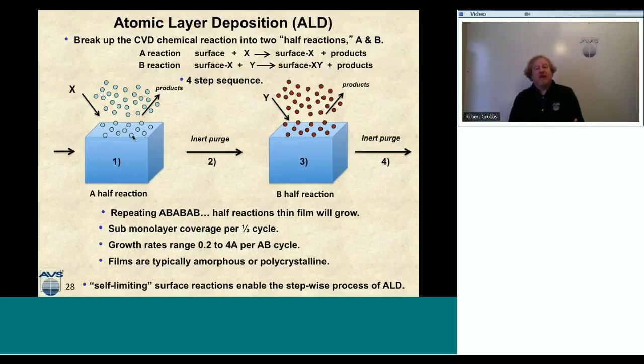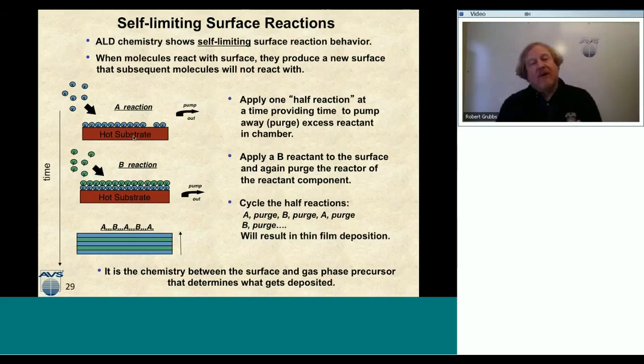So self-limiting surface reactions. This is the word that you need to know for ALD chemistry. ALD chemistry shows the self-limiting surface reaction behavior. So what does that mean? When molecules come down and react on a surface, they're going to produce a new surface. But that new surface will not react with any of those incident molecules coming down onto the surface. And this is considered a self-limiting surface reaction. And this is vital. This is critical to the process of ALD.